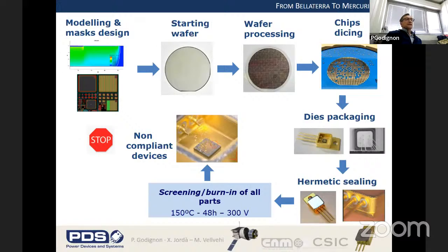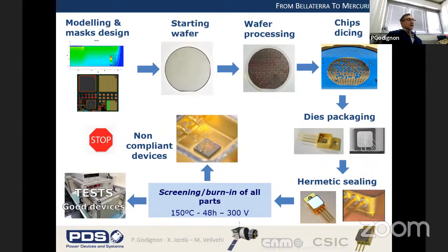And for instance, in this device, we observe that we had a hotspot on the periphery of the component in this red circle, which damaged the component. So we discard the use of this component. So all the devices which pass this burn-in phase can then be used for the qualification test and the test campaign as the next step for the application.